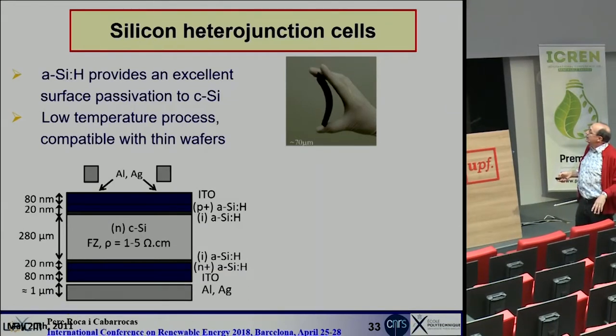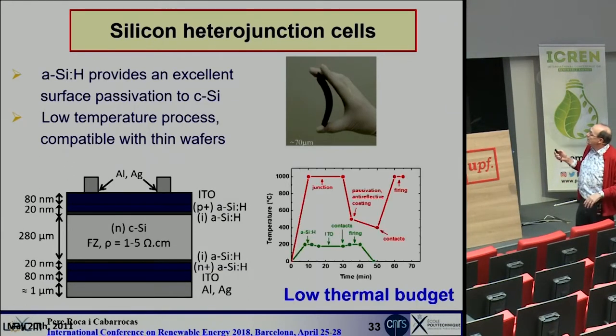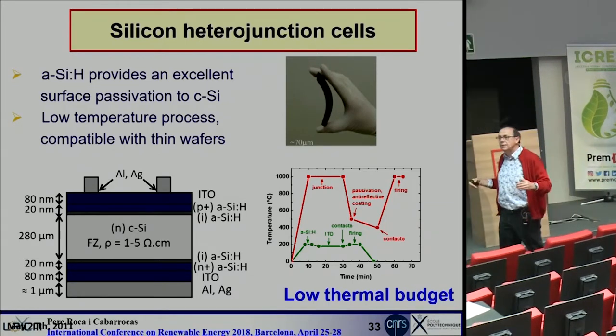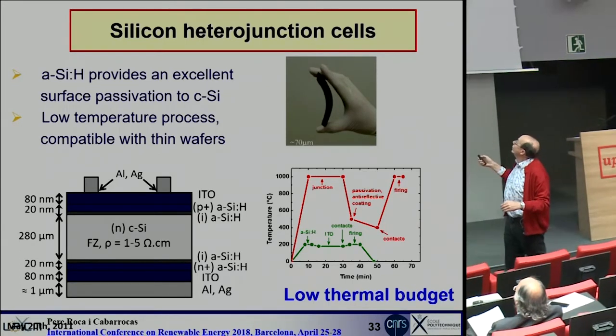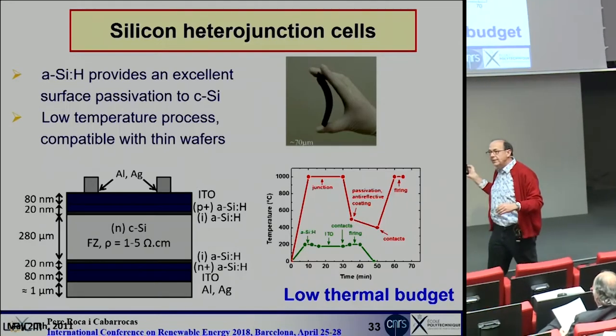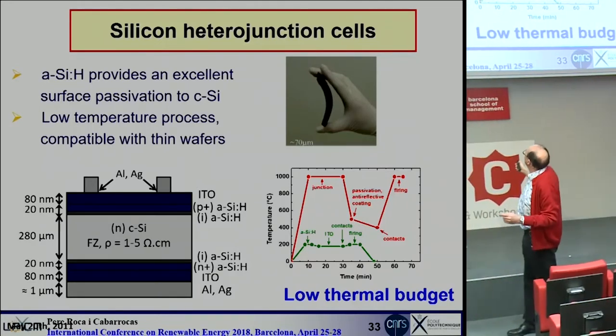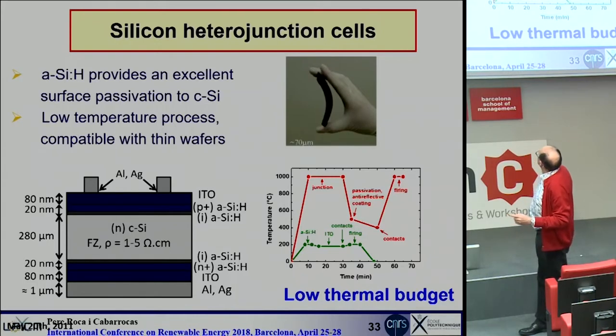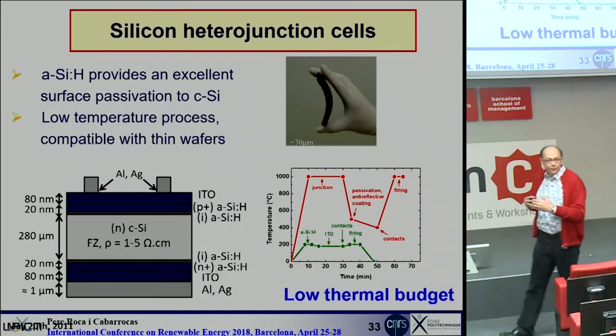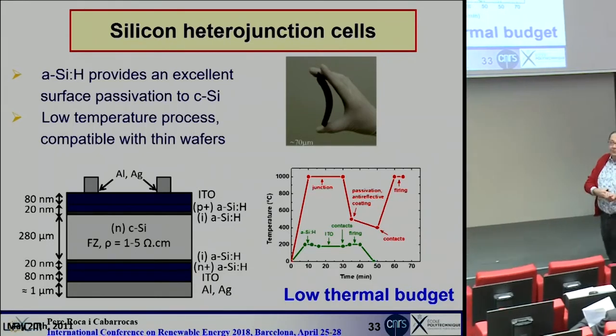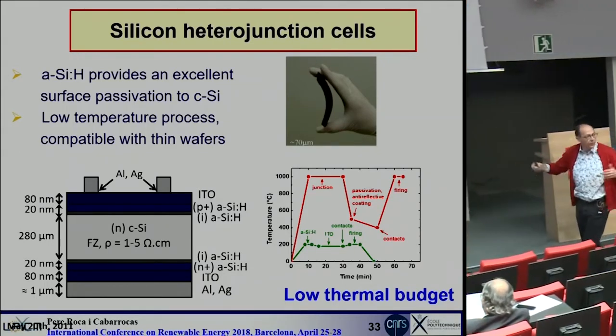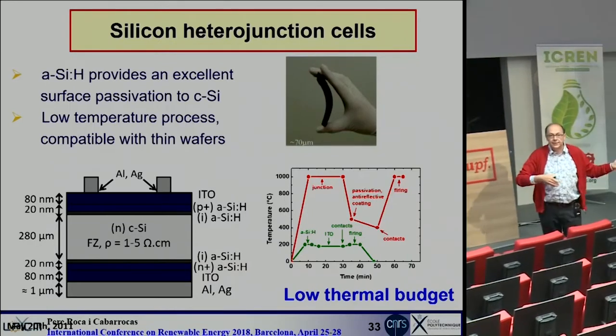The interest of this is that all this is taking place at 200 degrees. So we are reducing the thermal budget, and we are allowing to apply this on thin wafers. If you do this standard process of firing and diffusion on a thin wafer, it will just break because of the difference of thermal expansion coefficient. With a thin film process, you can work with 50 micron devices or even less.